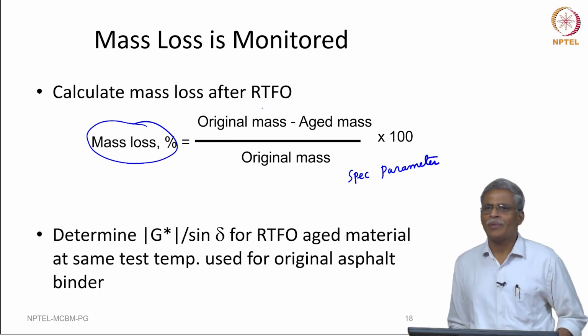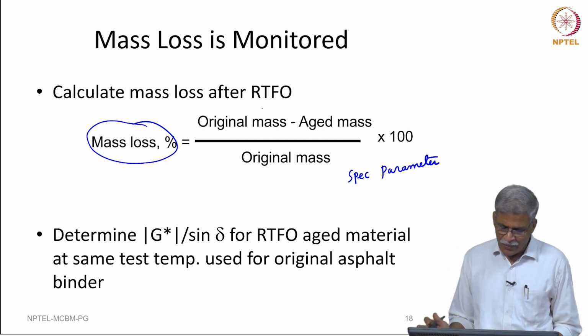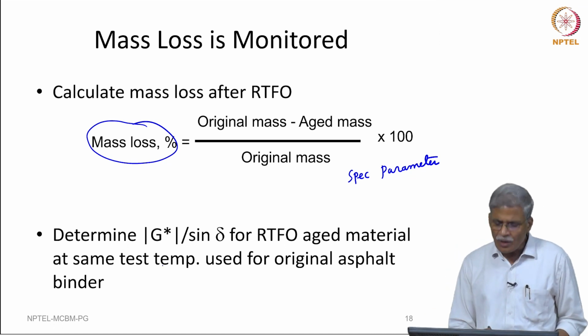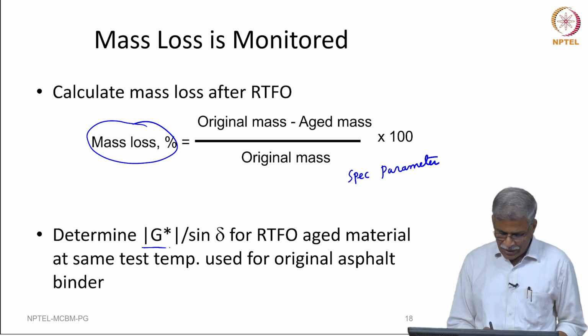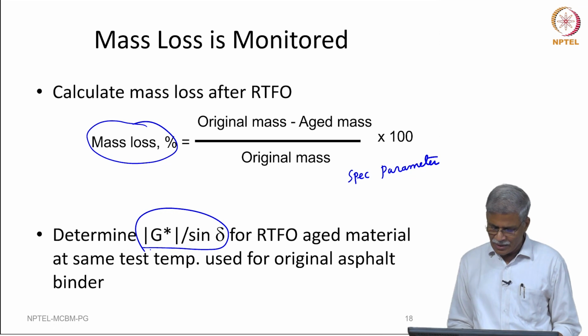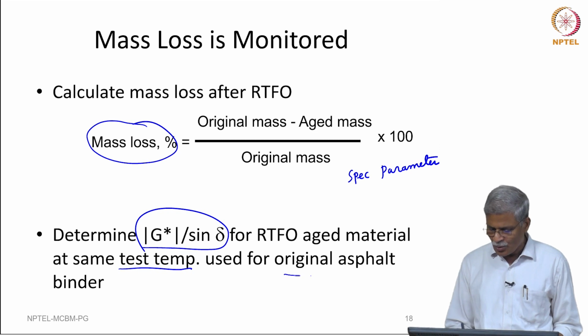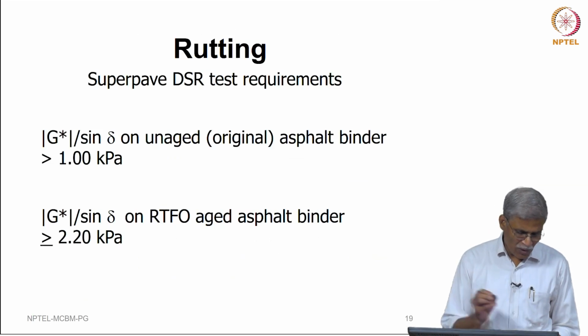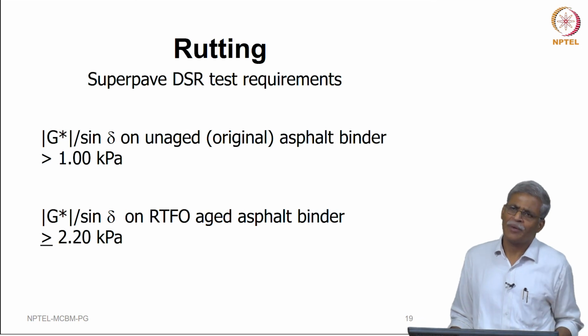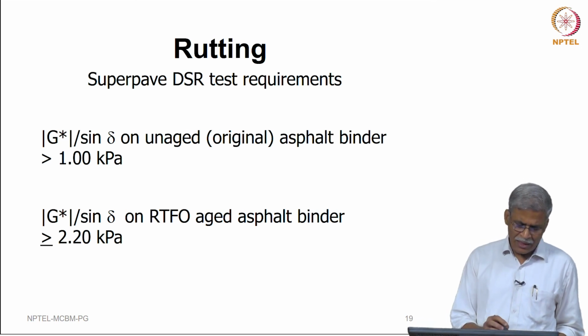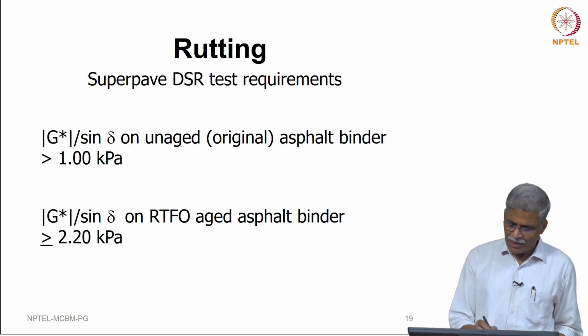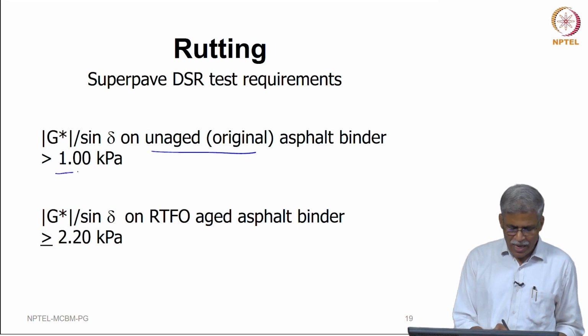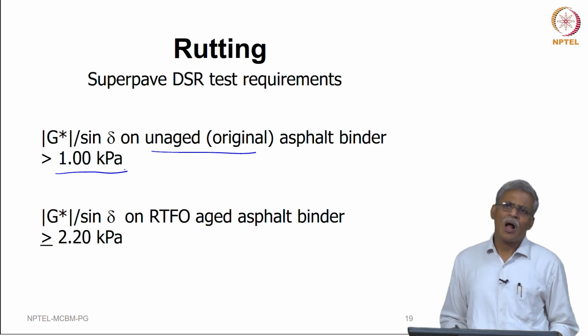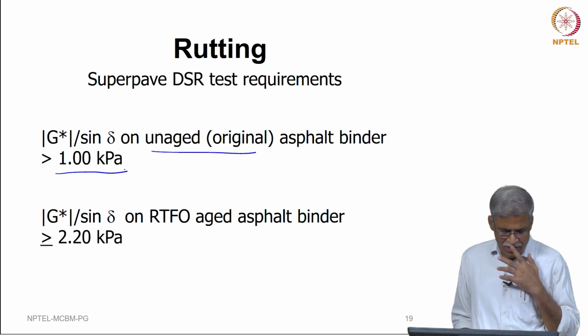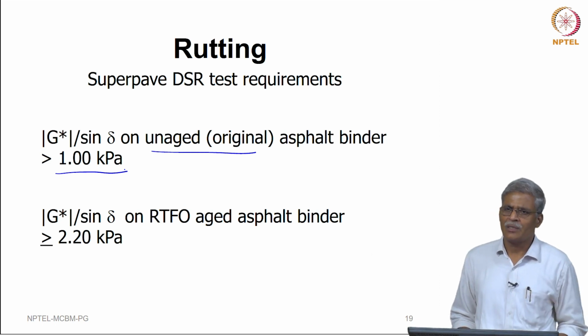So, the original mass minus the aged mass divided by the original mass, and then on this short-term aged material, we will be determining |G*|/sin δ for RTFO aged material at the same test temperature that we used for the original asphalt binder, okay. And what is the spec requirement here? The spec requirement clearly says that |G*|/sin δ on the unaged sample should be at least 1 kilopascal.